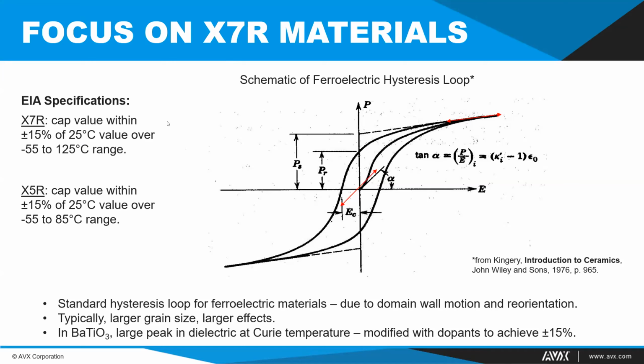X7R devices probably still make up on the order of 70% of the capacitors in the ceramic capacitor business, and they actually kind of vary into two groups, X7R and X5R. They're very similar devices, but the X7R range implies a capacitance control of plus and minus 15% of the room temperature value over the range of minus 55 to 125 degrees C. So that's a reasonably flat capacitance value over that range. The remainder of the market is largely made up of what we call NPO devices, which have far less than 1% over that range. So those are used in much more stringent environments, and their value tends to be lower.